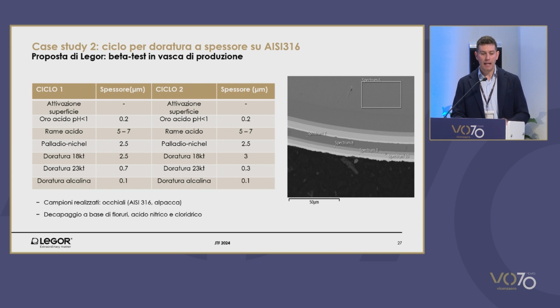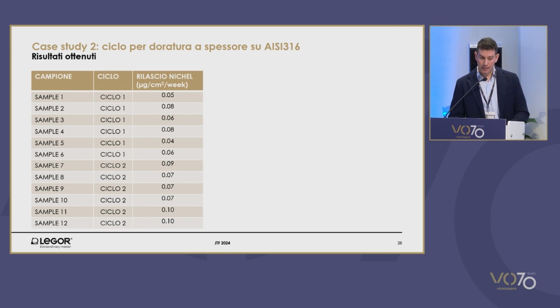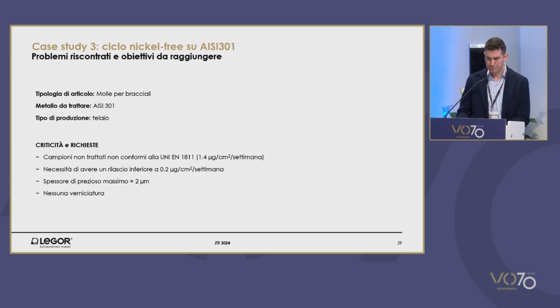AISI 316 was used, and treatment has been used with chlorides and acidic substances. The test performed showed that the release amounts of nickel are well below the threshold limits, less than 0.5. Both the electrodeposition cycles were effective. Now we're using cycle 2 because it's the one that requires the least amount of 23-karat gold.